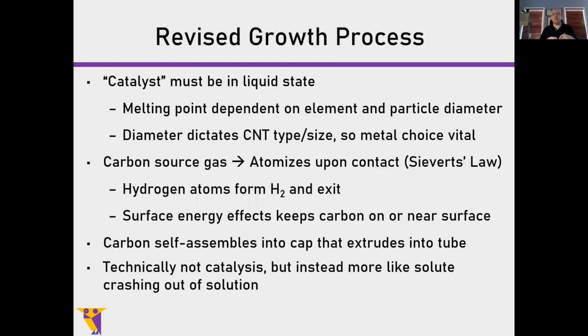And so the revised growth process is that the catalyst, again, must be in a liquid state. The melting point is dependent on the element and particle diameter. I mentioned ruthenium. I once did an experiment with ruthenium as the material, and we grew nanotubes, but because ruthenium has a different melting point, different surface energies and things like that, it shifted the diameters of the tubes that were made. So you have to choose wisely depending on what you want to make.